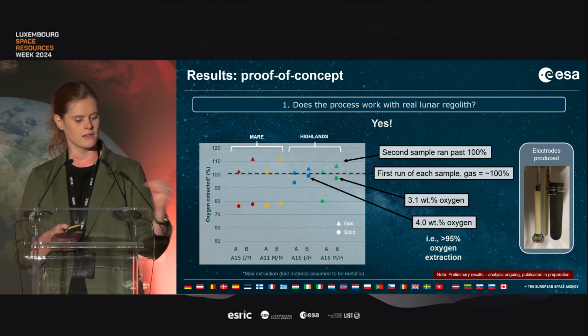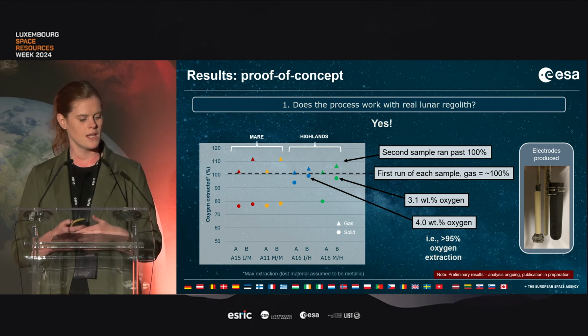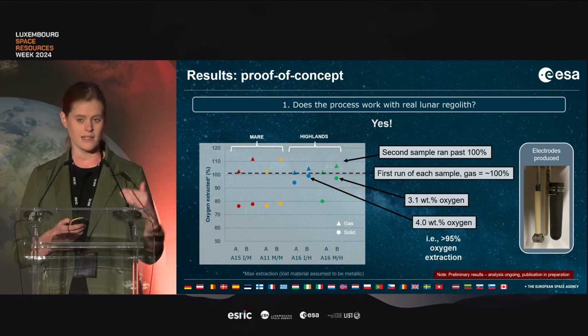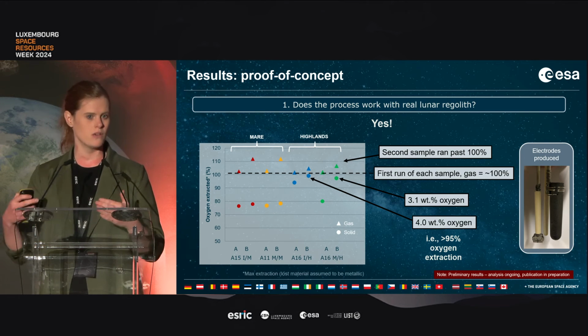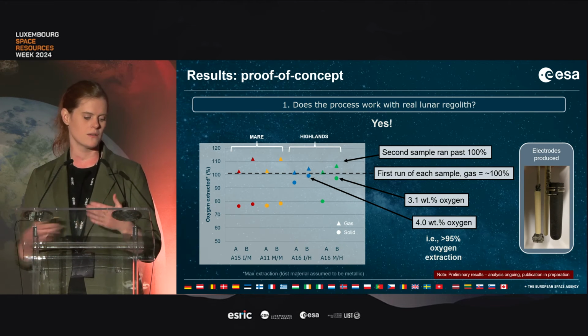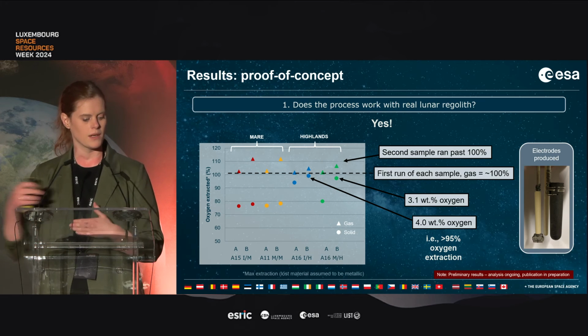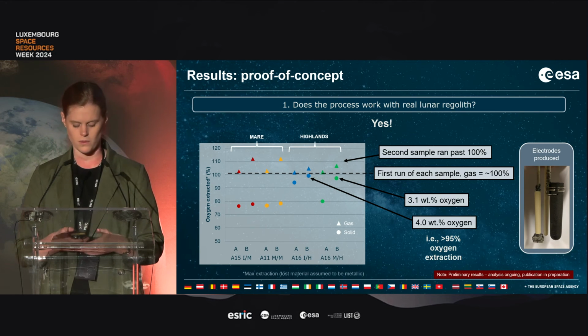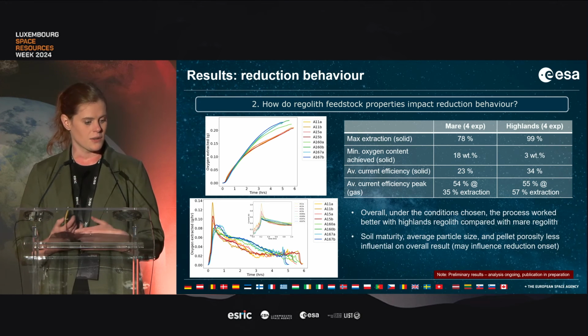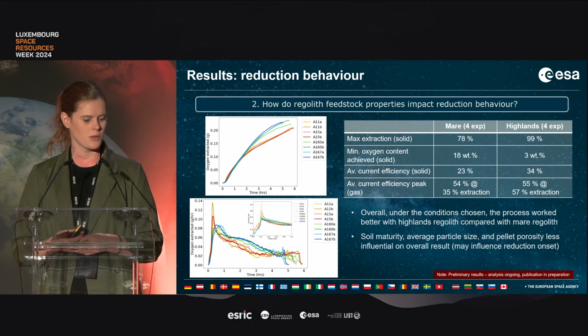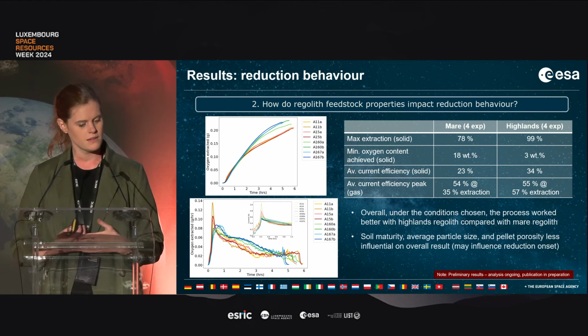With the Mare material, the red and the yellow spots there, we never got above 80% extraction, and even when overrunning the process a lot the second time round, we didn't really get much beyond, so the process had kind of stalled. That leads to the second question: how do the regolith feedstock properties impact the reduction behaviour?